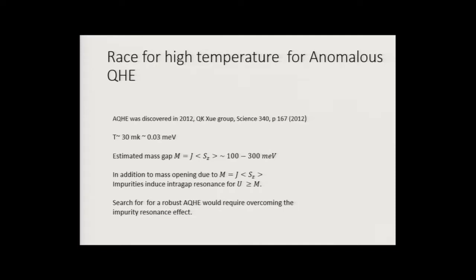So there's a huge gap of about 3-4 orders of magnitude in where they need to cool down before they get something that looks like, not roughly, it looks like a quantum Hall conductance quantization. And so I'm pointing out that this difference in the energy scales comes exactly as a result of the need to freeze out all the states inside the gap.